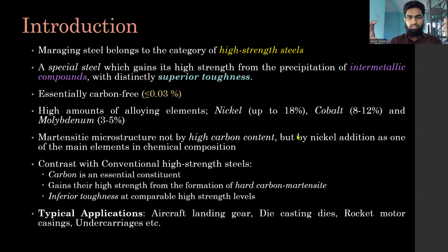In contrast with the conventional high strength steel, carbon is an essential component. A high amount of carbon is added, relatively high as compared to this steel. So that is one distinction. Another is that they gain their high strength from the formation of hard carbides. This is another contrast, and they have inferior toughness at comparable high strength. Though they are able to achieve those high strengths like maraging steel, they have inferior toughness. And this toughness property is very attractive to critical industries such as aerospace, tool and die, and the space industry.